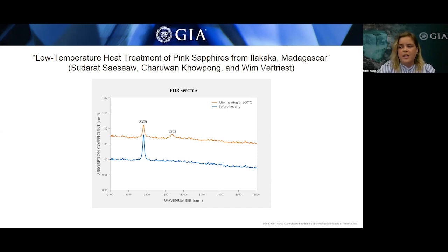Now, the authors also collected FTIR spectra on 250 additional unheated pink sapphires that were also reportedly from Madagascar. And 130 of these stones showed a single peak at 3309, with none showing a 3309 series.